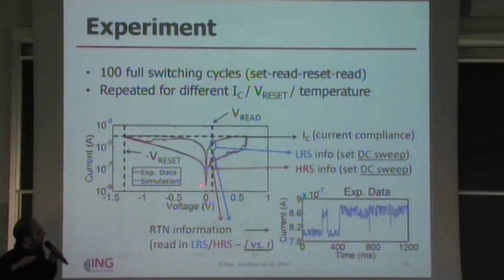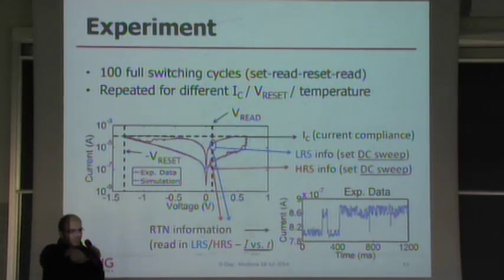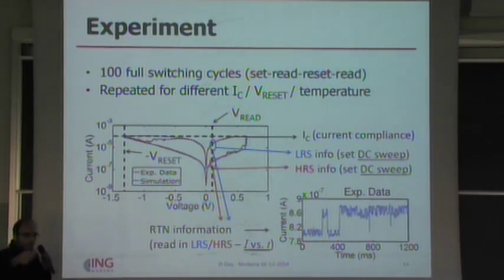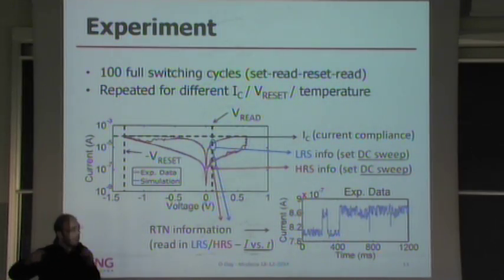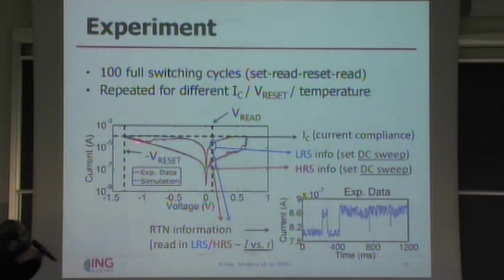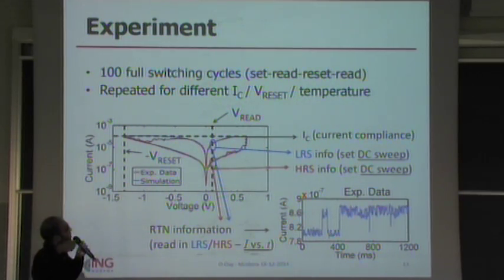So we set the device, and we have this first part of the IV curve. Then we read the device. We applied a fixed small voltage, 100 millivolts, typical example, and we read the device. We just sample the current over time. Hopefully we see RTN. Then we reset the device under given reset condition, and we read the device in HRS this time again. And we do this back and forth again and again for 100 full switching cycles.